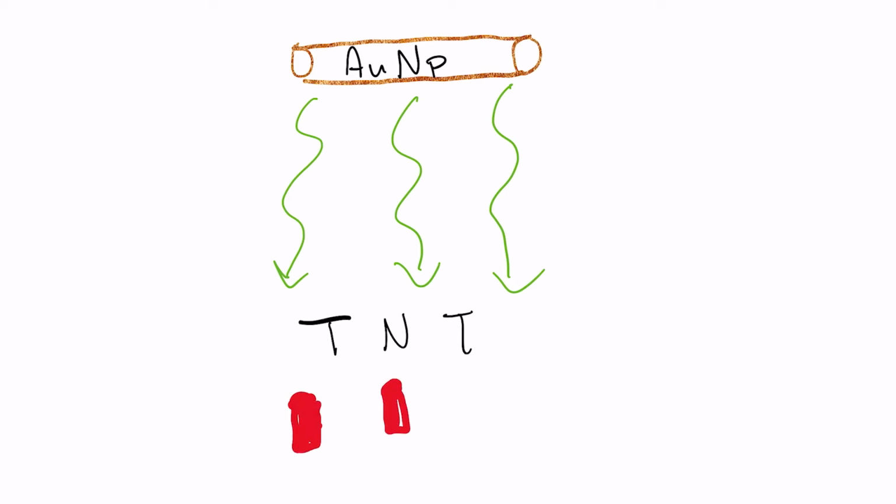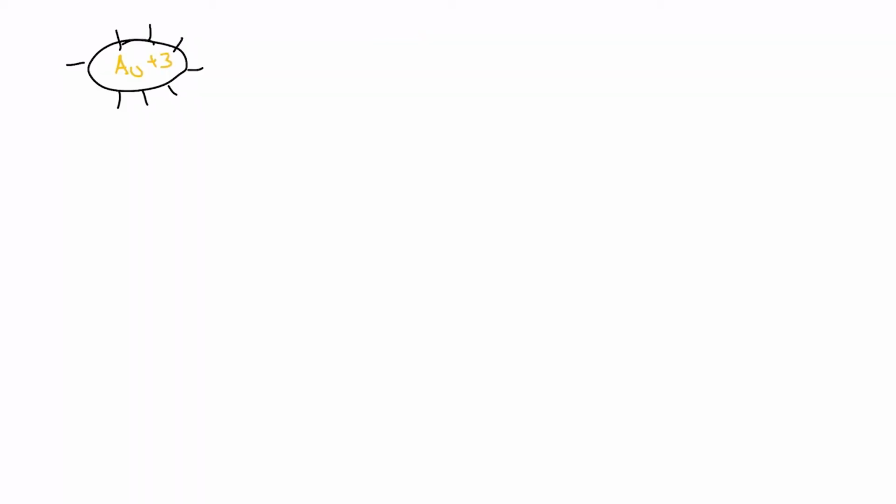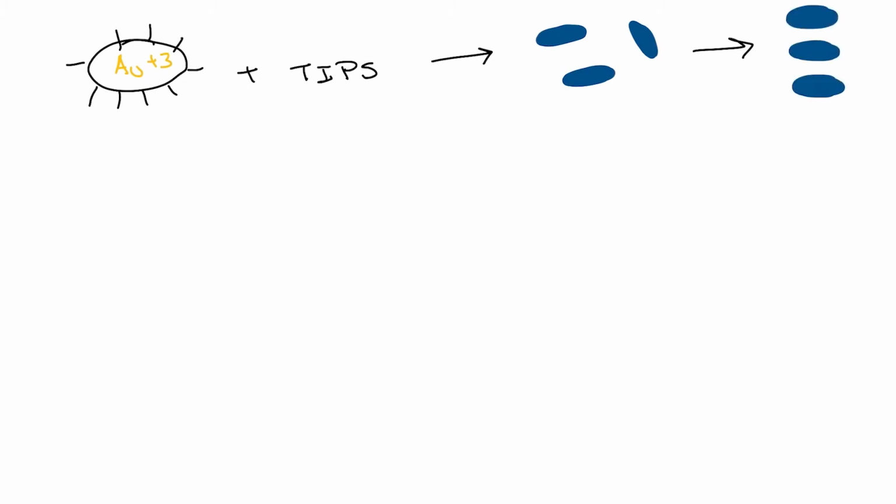Okay, so now moving on to a more in-depth analysis of the production of gold nanowires, here's Naomi. One of the methods used to create gold nanowires is by using gold(III)-allylamine planar complexes and triisopropylsilane. At first, gold(III) ions form complexes with a planar square geometry and are then gradually reduced to gold(I), forming disc-like structures by the aggregation of gold(I) and/or gold(III) complexes. Continuous stacking of disc-like objects leads to the formation of a cylinder.